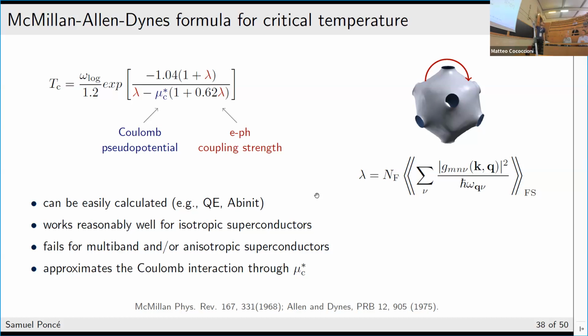And the only parameter that you need is the electron-phonon coupling strength. So this is just one number. And you obtain it by taking the sum or the integral over the Fermi surface of the electron-phonon matrix element, weighted by the phonon frequency. And you do this only on the Fermi surface, and you get one number that you can plug into this formula. You have this empirical Coulomb potential. This describes the electron-electron interaction. And then the omega log is a weighted phonon dispersion. But again, it's just one number. So this is easily calculated. You get it from the output of Quantum ESPRESSO, and so on.